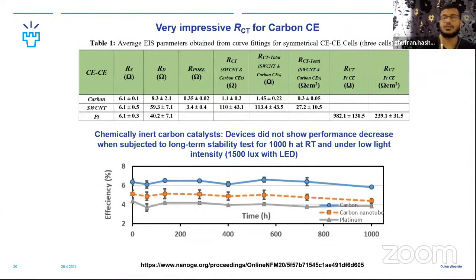So we decided to soak these devices under a very low stress condition, meaning that we soaked the devices under an artificial LED based lamp at 1500 lux. And as you can see here, the carbonaceous material also showed very good chemical inertness, and they did not show any degradation. So that is a very promising result if you see it from the perspective of long term stability reports that have been coming up now with all these alternative sets of material.